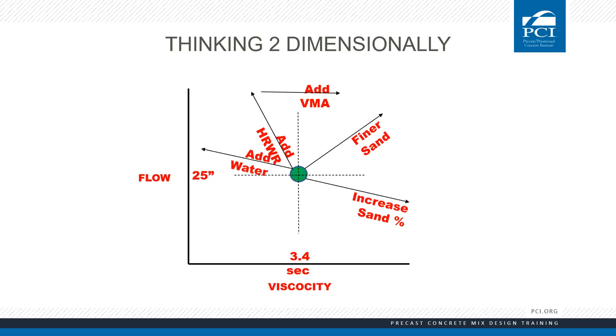Let's say we want to increase flow and viscosity both — that's the top right corner of the rheology chart. You could increase your high-range water reducer and then add a VMA. High-range water reducer increases flow but lowers viscosity; the VMA increases viscosity back, giving you higher viscosity and higher flow. Is there another way? Yes — we can use a finer sand. Notice: increased sand percentage lowers your flow, but using a small amount of finer sand increases flow and viscosity. What's cheaper — using a finer sand or adding extra superplasticizer and VMA?